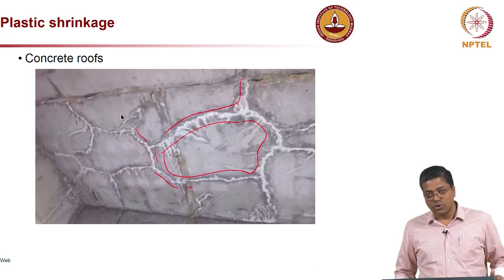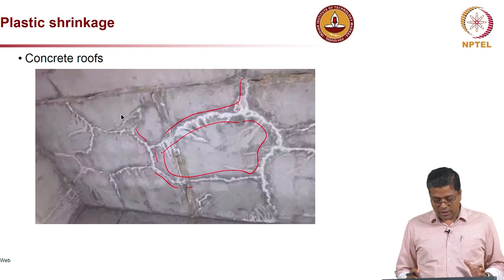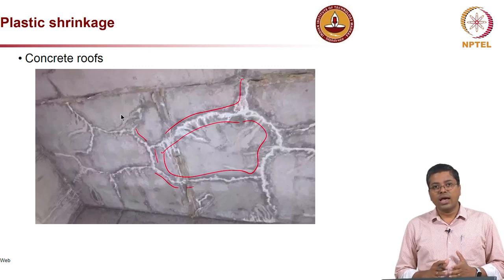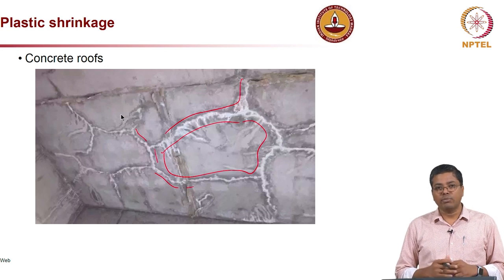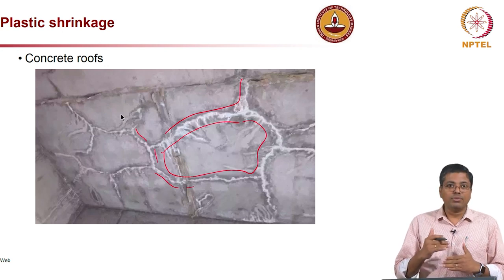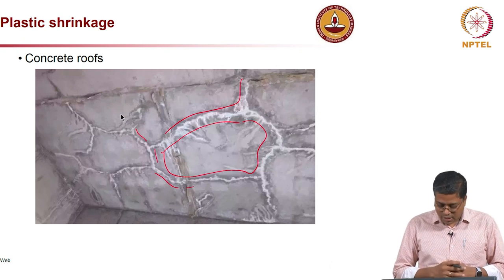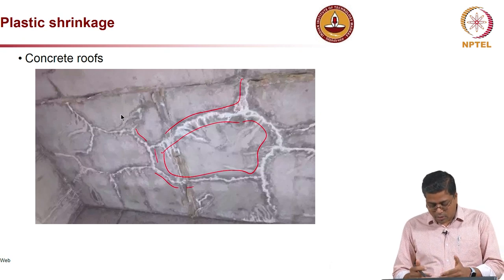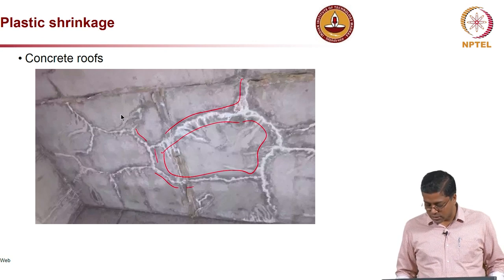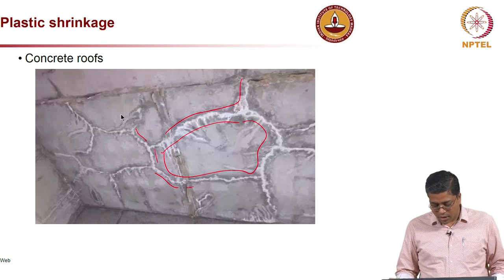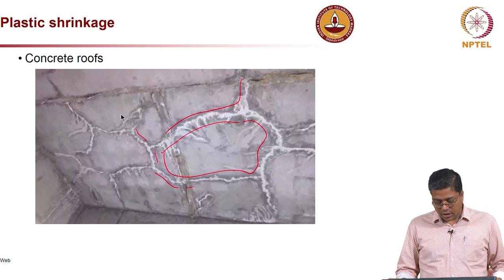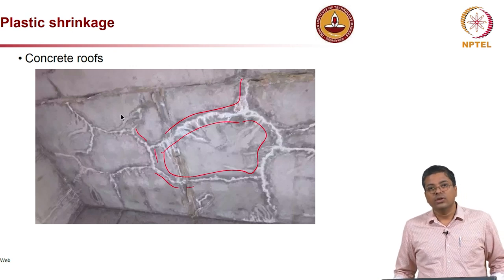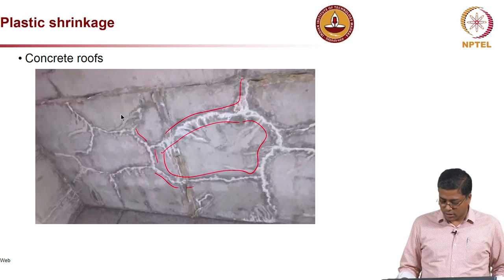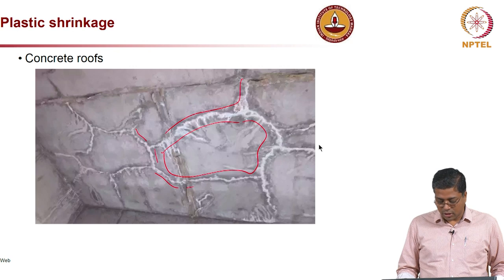And one thing to note here is these are not structural cracks, because you can see very clearly that there is no particular shape to it, and it is a through and through crack, meaning from the top of the slab to the bottom of the slab, the crack is continuous, and that is why you see these white patches also forming. And if it is a roof slab, then definitely you will have issues during the rain. So, it has to be protected, or treatment has to be done before you can go further.